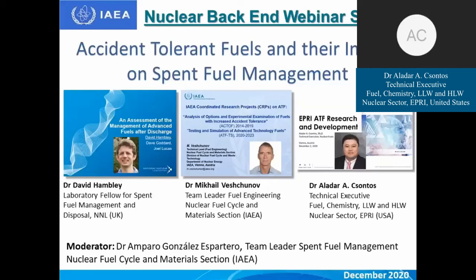The other area was also not just the thermal aspects, but also the dose aspects, and in particular the steels. There are operational examples out there of facilities that used stainless steel prior to going to zirconium alloys, and in one case in the United States, one set of transportation had to be delayed by almost a decade compared to the Zirc fuel that came out much sooner, because of the activation of the stainless steel. You have a higher dose, so you can't transport those because you'd be above the dose limits. So the time to when you can take the fuel out and transport it to a centralized facility or an interim facility could also be delayed by going to some of these concepts.